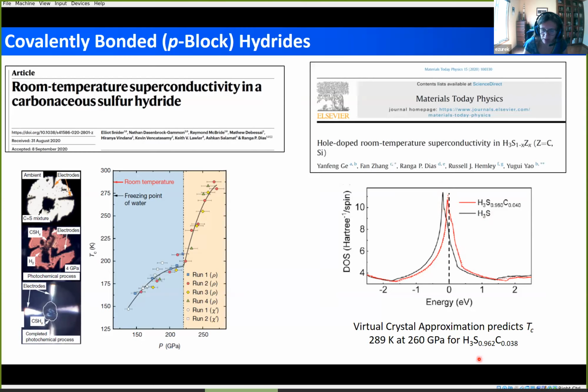This could be accomplished by doping, for example, by carbon of about 3.8%. There were calculations done with the virtual crystal approximation that found TCs that were really quite in line with the experiments. So we wanted to take it to the next stage, going beyond the virtual crystal approximation and actually introducing carbon atoms into the system to see how this would perturb potentially the bonds within the lattice, and then afterwards affect the superconducting critical temperatures.